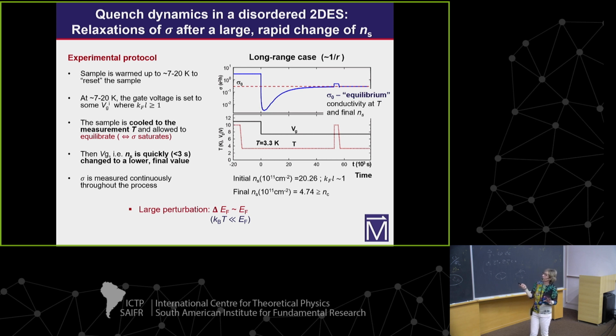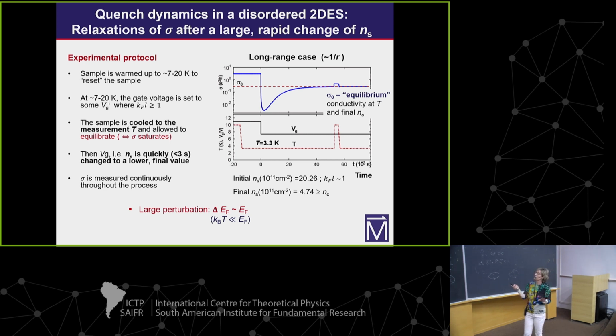Here, what we do first is cool the system down to the measurement temperature, in this case 3.3 Kelvin. Then sometime later—it doesn't matter when—we change the gate voltage. We go from very high density, where nothing interesting happens, and reduce it quickly within our time measurement resolution, within a couple of seconds. So the total carrier density decreases very quickly.